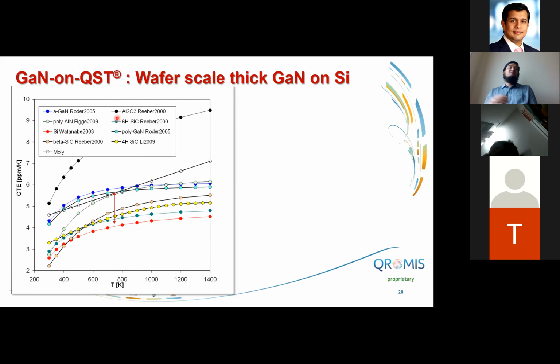So to explain this problem a little bit more, here we have the temperature on the x-axis. On the y-axis, we have the so-called CTE, or coefficient of thermal expansion mismatch, of different gallium nitride substrates. The red line with the dotted points is the data for silicon, and the blue lines are the gallium nitride. So we see that there is a large difference in CTE, which will cause the device to crack when we try to grow thick epi on it.